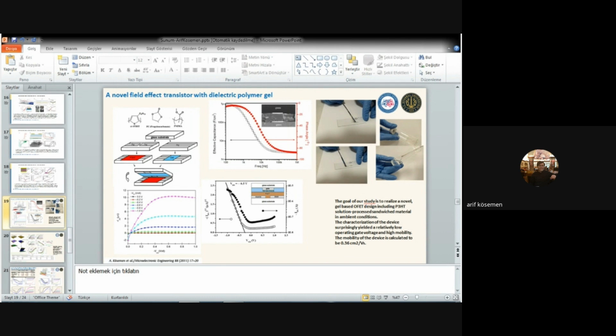If you use pure PMMA as the gate dielectric material with P3HT, you get about 100 volt operation voltage. But with plasticized PMMA, we get a transistor under 1 volt. This is very important for flexible electronic applications. And you can see here the operation and the transfer characteristics of our transistors. We also characterized the capacitive properties of the gel structure. It has a very high capacitance value, almost 1 microfarad per centimeter square.